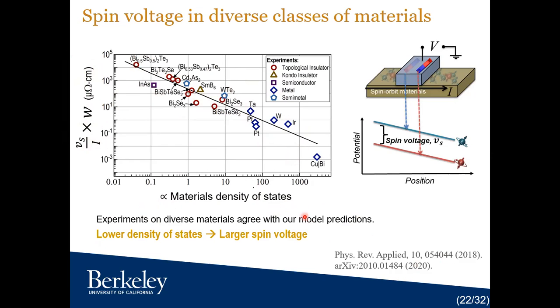So what this tells you is that if you have a material with lower density of states, your spin voltage will be larger, and that has the potential to lower the write current. So we are interested in lowering the write current.